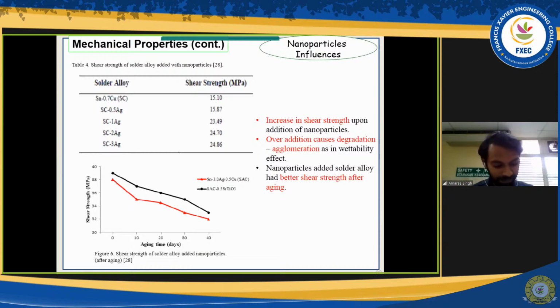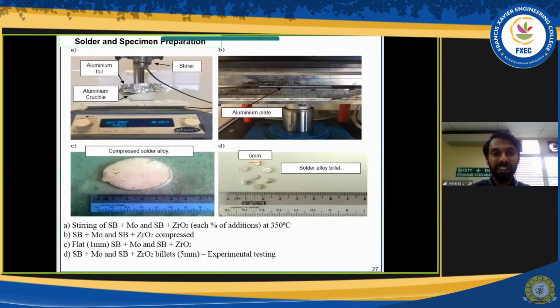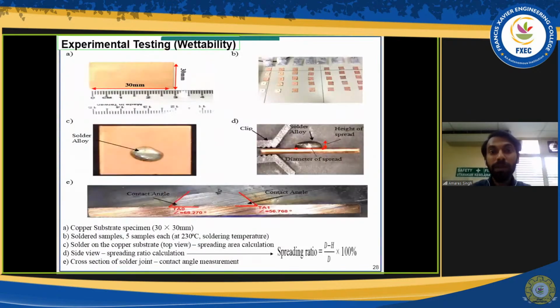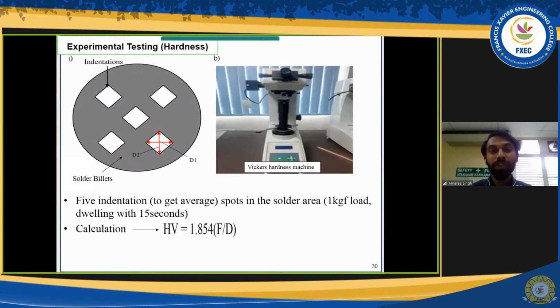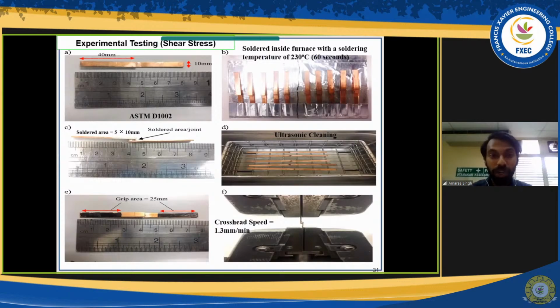Thank you, sir. There's another question posted here. What about the processing speed of this one? Yes, sir. This is a good question. If you ask me, we must use a standard procedure so that we are following what is happening in the real world. ASTM D1002 has provided us the speed. The speed here, I can assure you, is mentioned as 1.3 millimeter per minute. I didn't come up with this figure. This is according to the ASTM standard. Different standards have a different speed for a different material. Since we are dealing with solder alloys, soft materials, in accordance with this ASTM, we must be using 1.3.